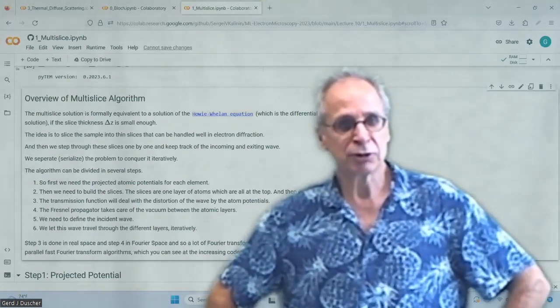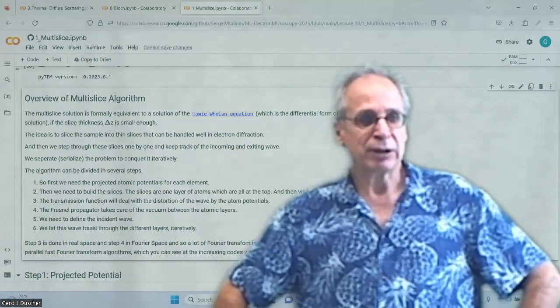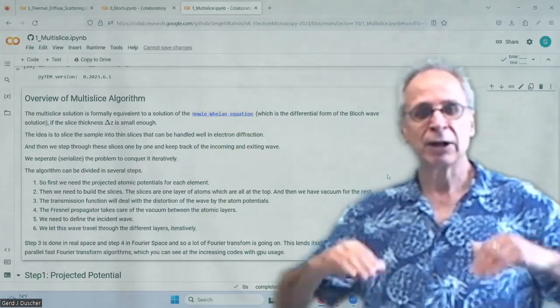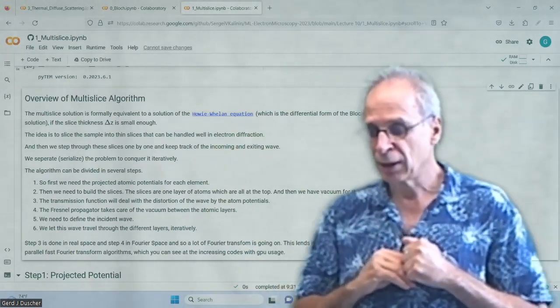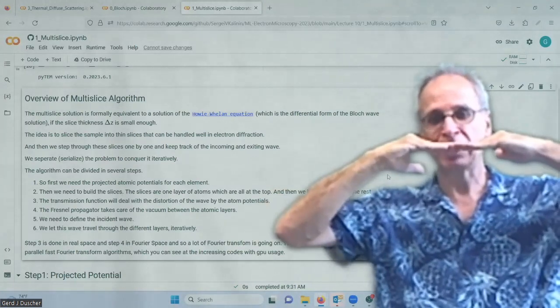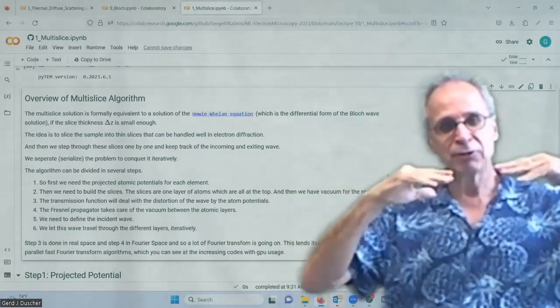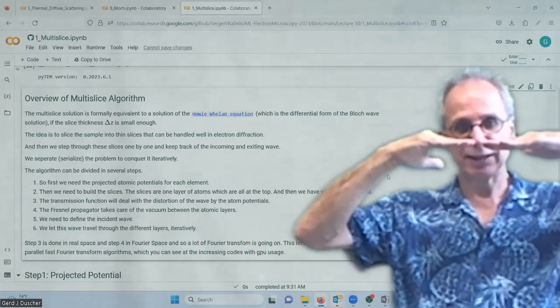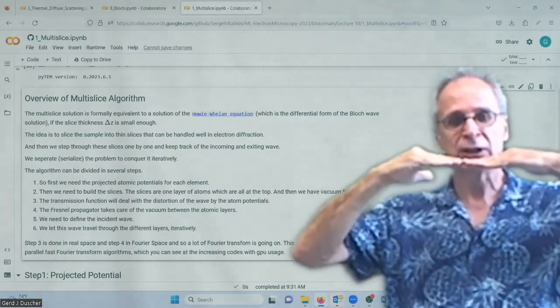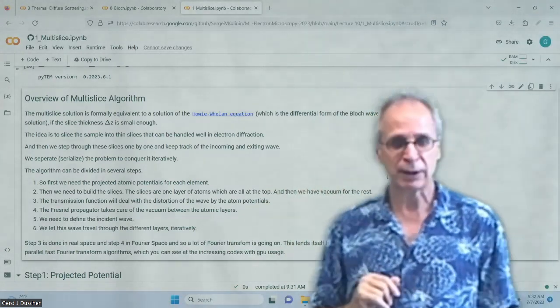The multi-slice algorithm of the Howie-Whelan equation: we separate out our problem, but now not in terms of quantum mechanical differences, but we slice our crystal. Within each slice we have our potential where diffraction occurs, and after that we come out with different angles — different phases depending on what angles were introduced. We have different phase shifts from one slice to the next. The incoming wave comes in again and we go through iteratively. This gives a lot of flexibility and you can build relatively large models.